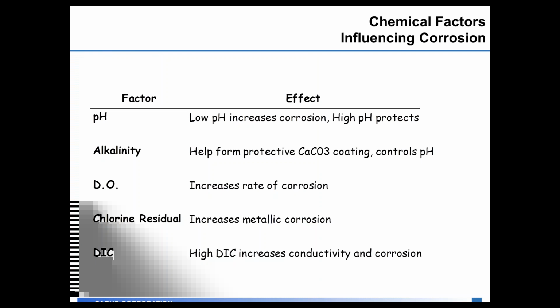So when we talk about corrosion, these are the standard factors that we would look at. pH is always the number one that you measure at a water plant. We know that low pHs below 7 are acidic, and they will increase the amount of corrosion in your system. As you increase pH, that typically protects the system, and so pHs in the 7 to 8 range, or going higher from 8 to 9, tend to be protecting for the distribution system.